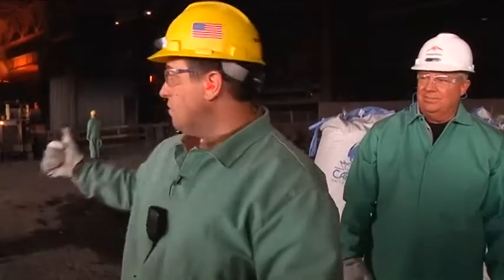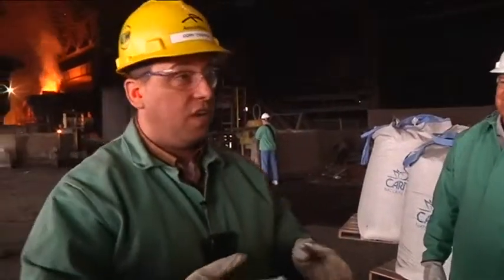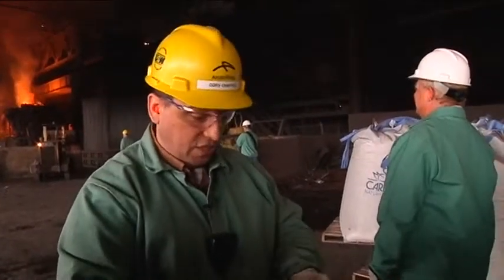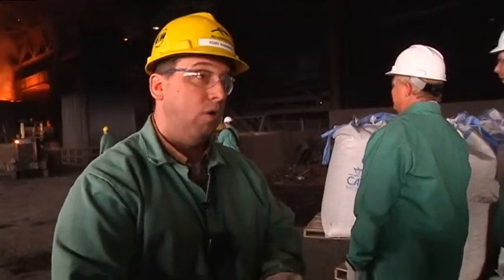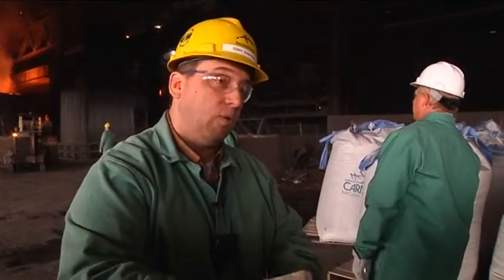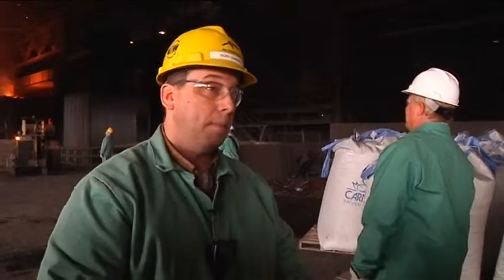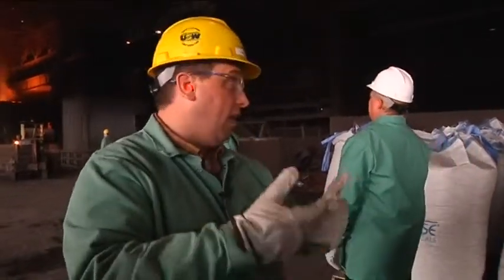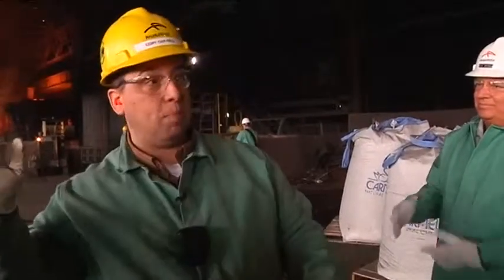We have a tapping sequence in the furnace that's an automatic tapping sequence, which is unique in the industry. What happens is in the bottom of the furnace, there's a tap hole. The furnace tilts, the tap hole opens automatically, and then the liquid starts to transfer into a ladle underneath. As the weight goes into the ladle, the furnace will continue to tilt until we get within 5,000 pounds of the aim tap weight. Then the furnace quickly rotates back to a negative direction, stopping the tap. That's one way to avoid slag into the liquid.